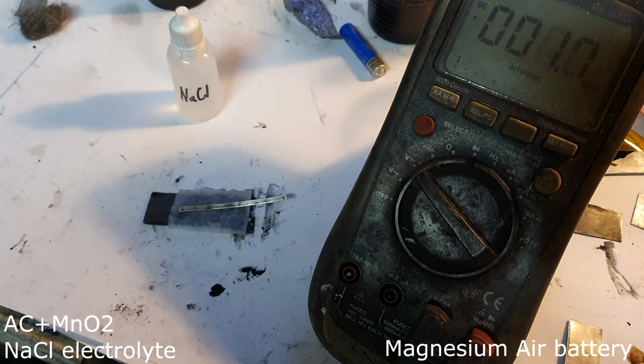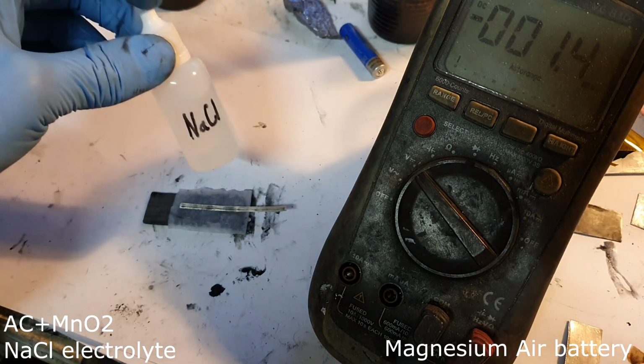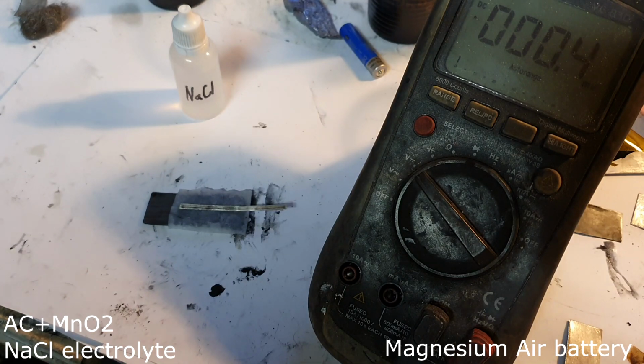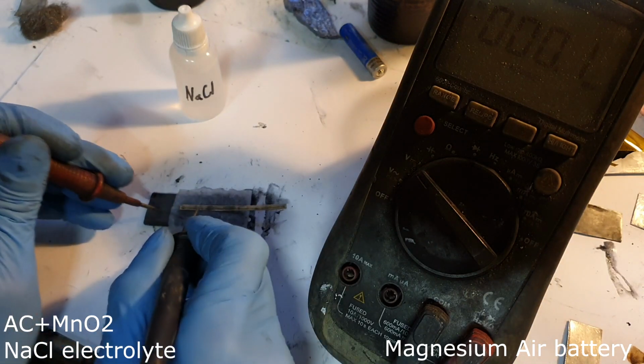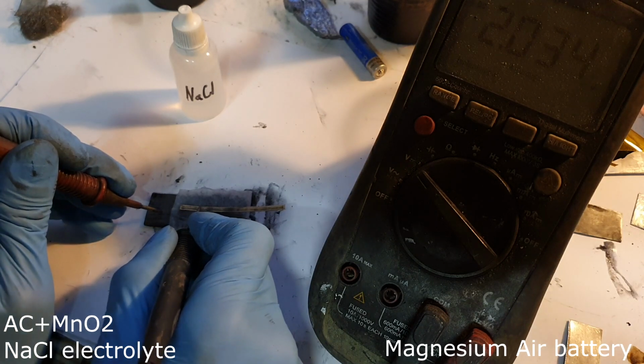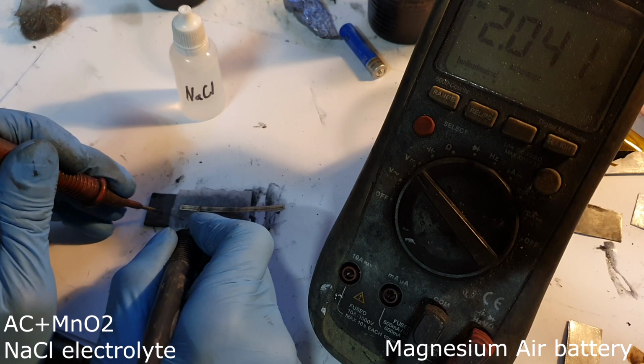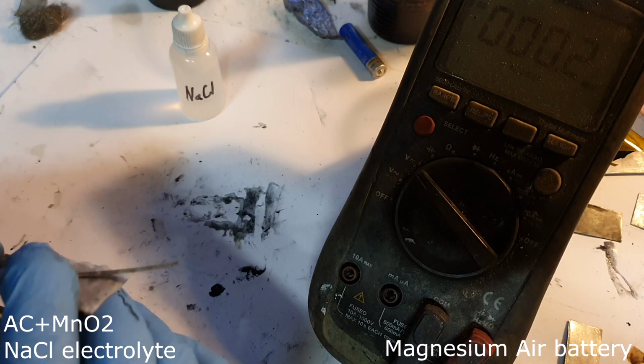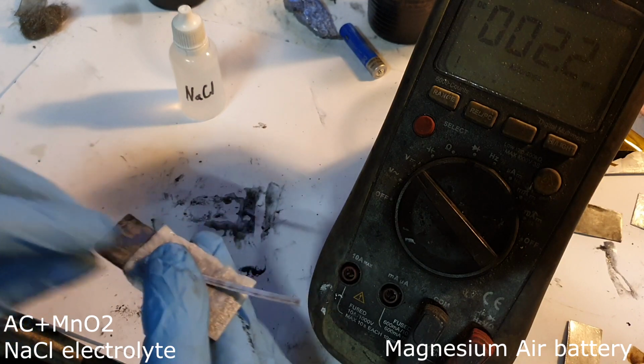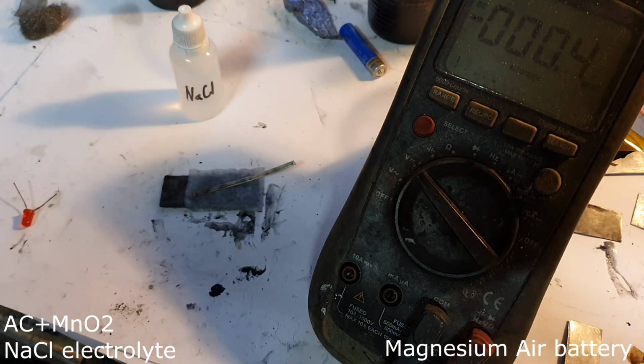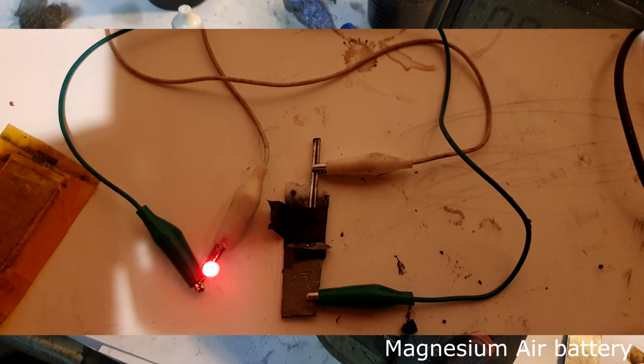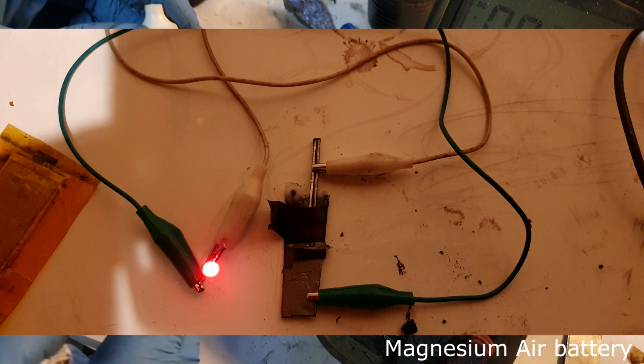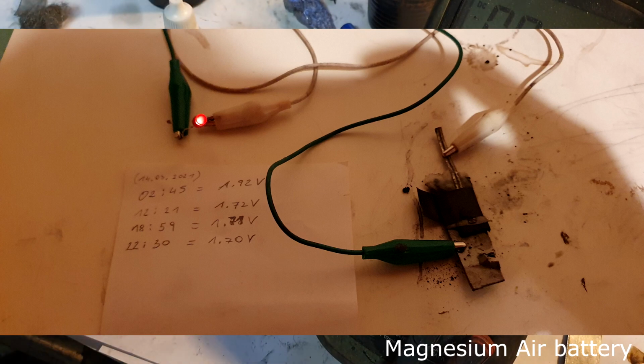And the last magnesium air battery still has the electrolyte of sodium chloride, but has some small amount of manganese dioxide. And I get 2 volts really easily. Nice. So this one I also tested for several hours, and after several hours this magnesium air battery, which is based on sodium chloride and also has some small amount of manganese dioxide, has run the LED for several hours already.